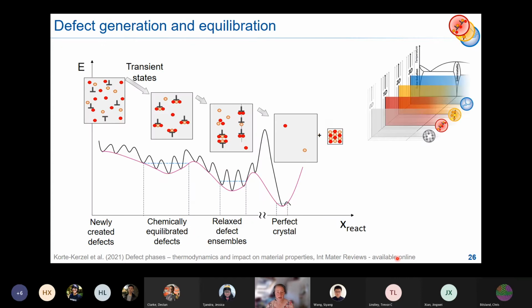How will these actually form? Well, what you will get is something that we know from all other defects. You start with newly created defects and maybe a random distribution of alloy elements depending on how you quenched. And then you have some transient states where the elements will actually segregate to the defect, form the most favorable defect structures. Then you'll probably get some relaxation and formation of defect ensembles, like you get, for example, in recovery.